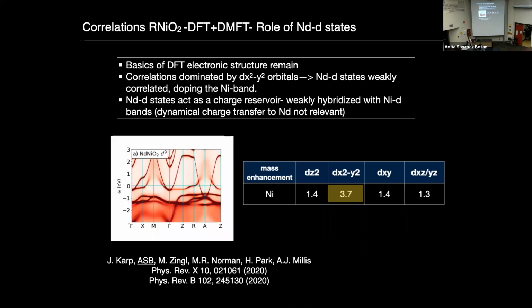Now, these materials, of course, have strongly correlated electrons. So we wanted to look at correlations a little bit more carefully using dynamical DFT plus DMFT, that's density functional theory plus dynamical mean field theory, as a more appropriate tool to look into that. In particular, we wanted to look at what role those neodymium D states play. Are they simply a spectator, or do they actually play a deeper role in the electronic structure of the material?